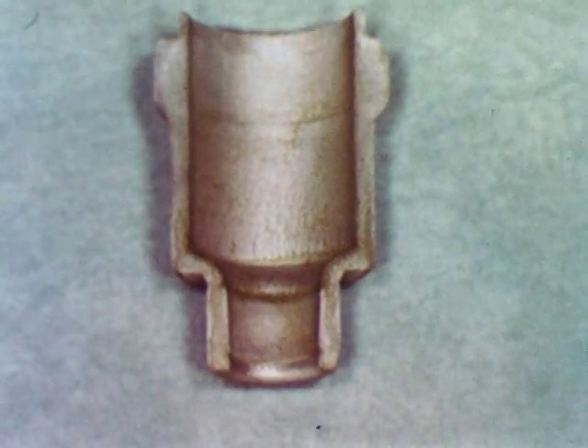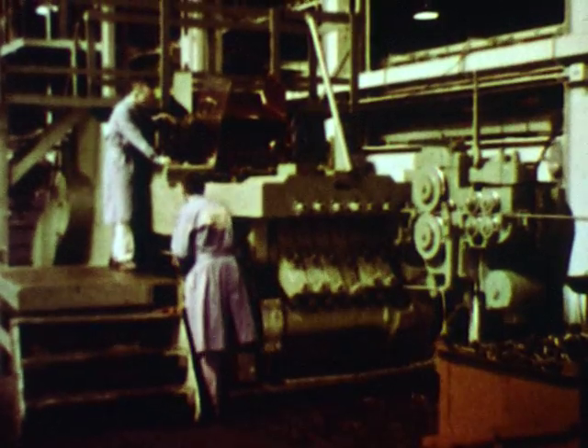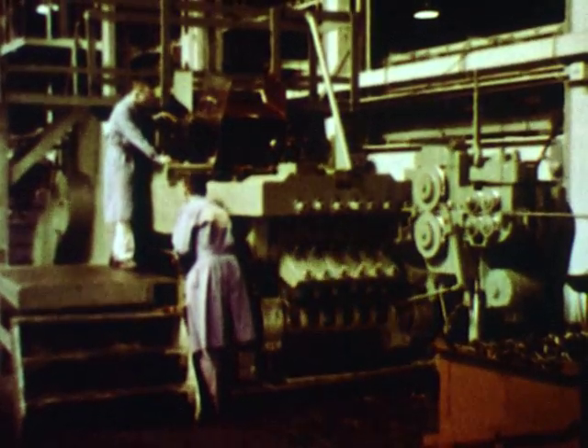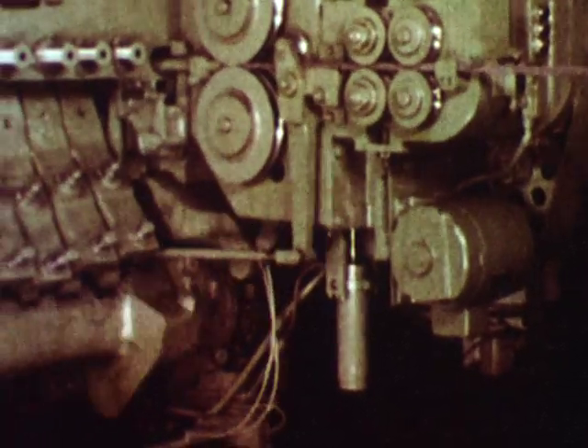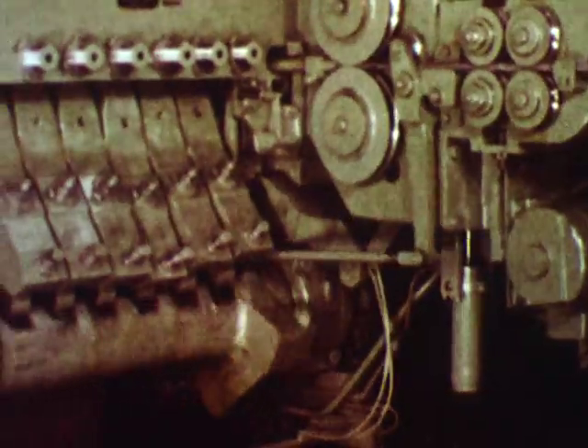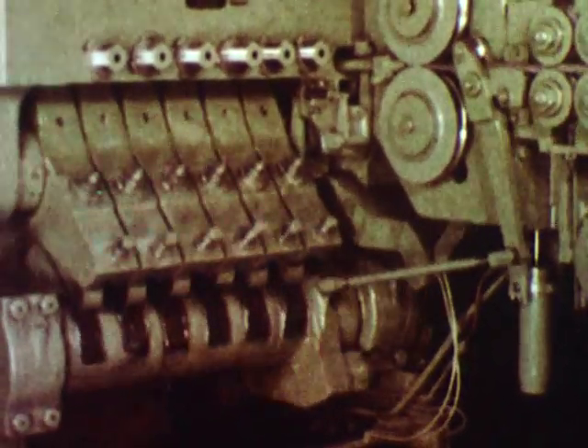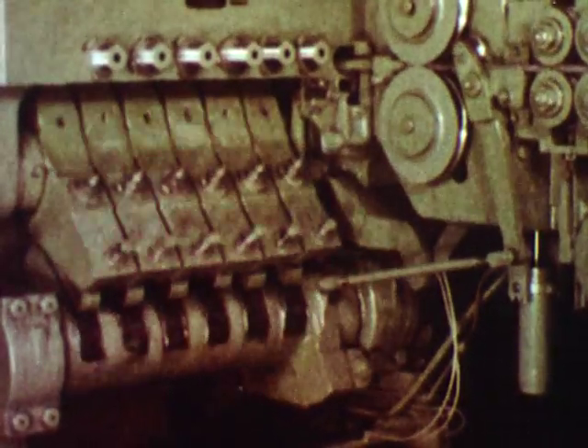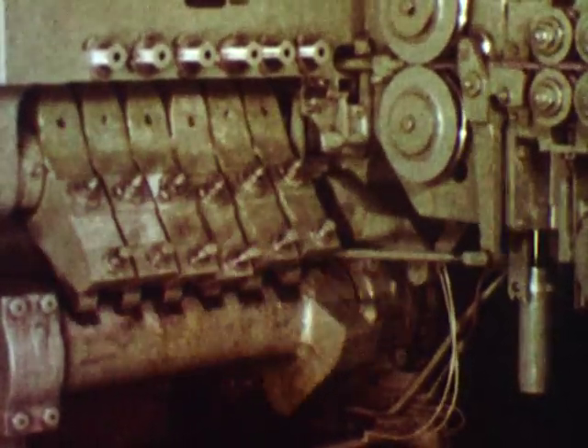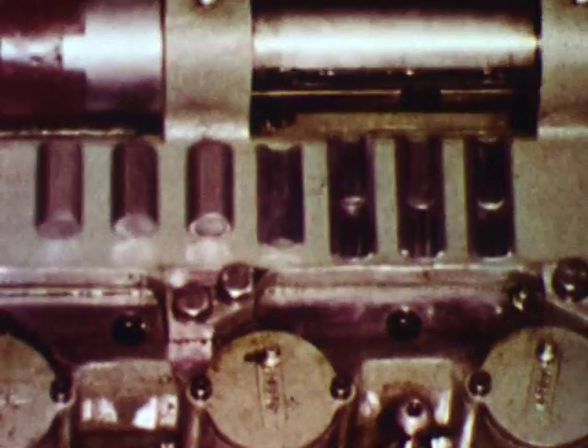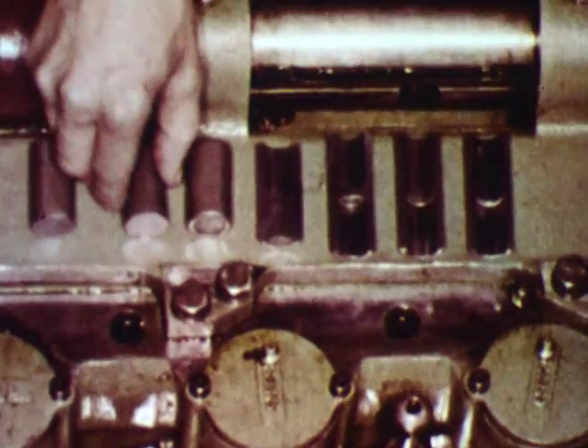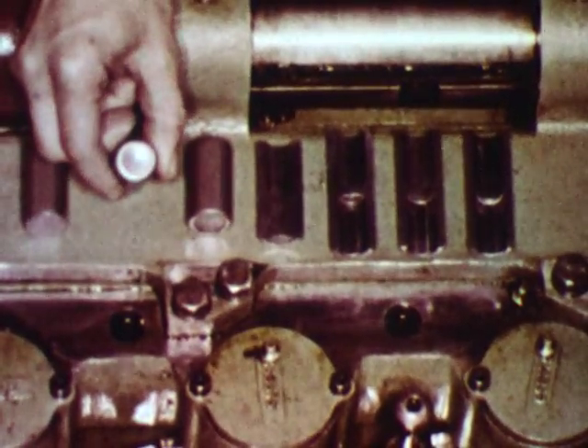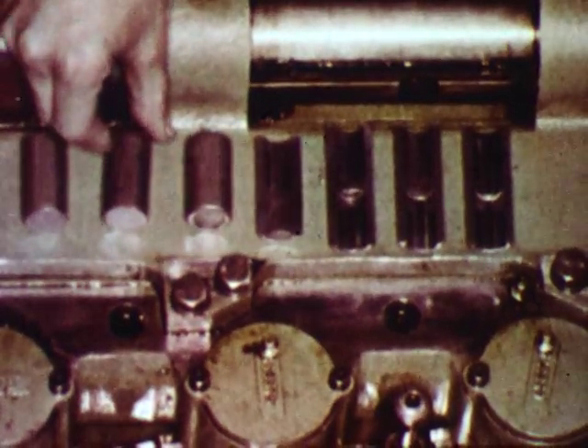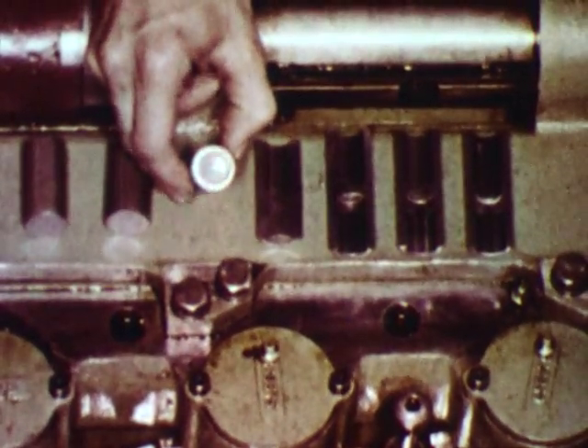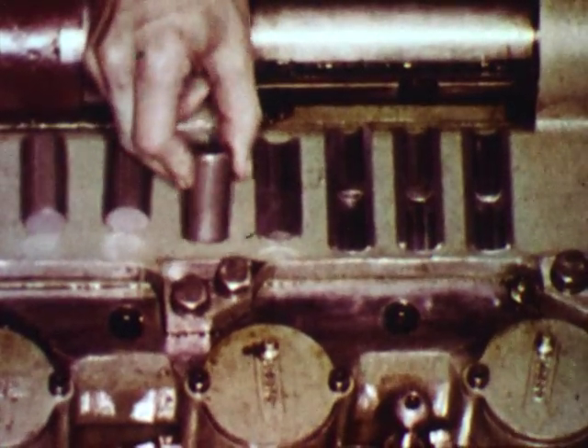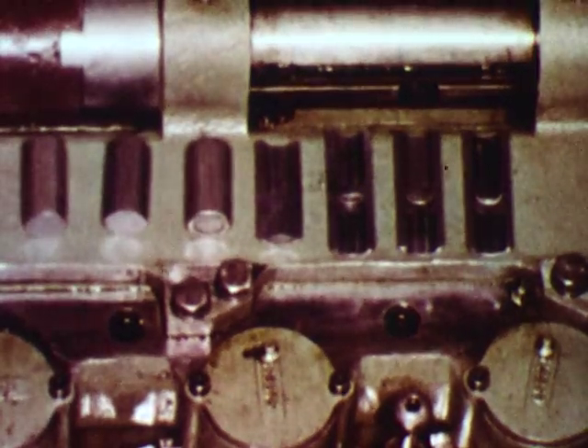This ensures maximum strength. And finally, the latest in automatic cold forging machinery, a number 1000 7-station 6-die cold former, capable of great versatility and flexibility in producing unusual parts formerly considered impossible. Automotive piston pins are produced from 1019 coiled wire at 50 per minute. Starting with 1-inch diameter wire, this 6-die machine produces a part so perfect that grinding the outside is the only machining necessary. There is only 3.5% waste in the small slug punched from the center.